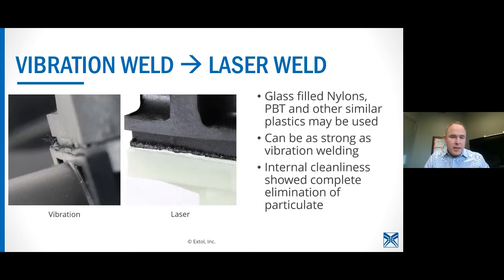What we'll see here is a couple images. For confidentiality's sake, we've got some very close up, and we'll speak in generalities, but you can see a typical vibration weld. This is a glass-filled nylon application on the left, where you see a variety of different kinds of flash. You can see angel hair, dust, inconsistencies in vibration welding, and a similar material and application on the right, where we did a laser welding application. You can see a much smoother, to some degree more uniform flash, and actually substantially less. These two images don't quite show them scale to scale, but this is a very common situation with difficult to weld materials, glass-filled nylons, PBT.